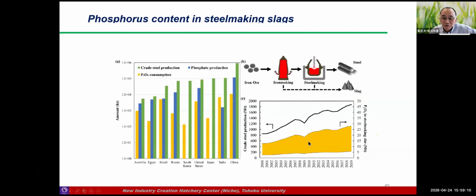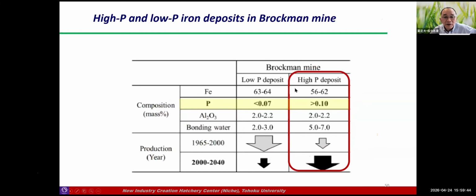But if you see this one, the amount of P2O5 in steelmaking slag is a huge amount. Once we can recover this P2O5, it could almost easily supply an amount comparable to the P2O5 consumption, probably much more. So this is a very attractive phosphorus resource.